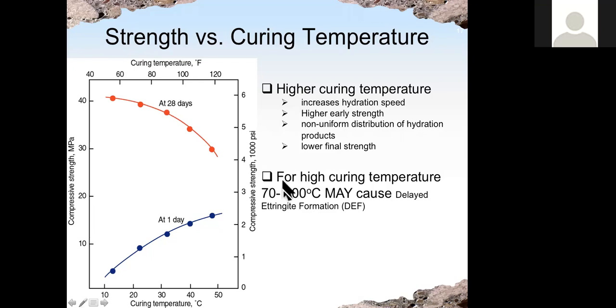And again, if the curing temperature is above a certain level, that may cause delayed ettringite formation. The high temperature actually will dissolve the ettringite in concrete, which is formed at early age due to this high temperature, and then when the temperature drops down, ettringite will be formed again in other parts of the concrete. Because ettringite formation will cause expansion of solid volume, the concrete may crack due to this delayed ettringite formation. We're going to talk about this more when we talk about sulfate attack in concrete.